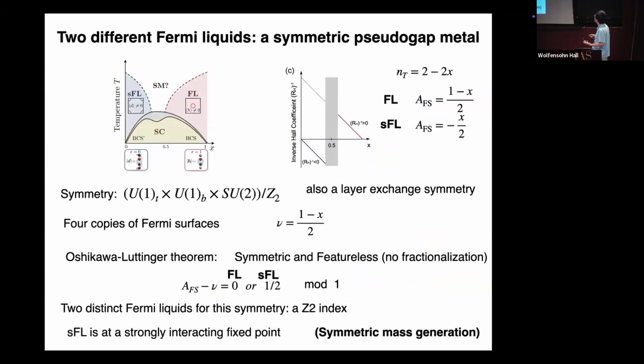It turned out it's possible if you consider the normal state. For example, in this regime, you can consider D condensed but H gapped. It turns out this gives you a small hole pocket. It's a Fermi liquid with a small hole pocket. The picture is almost trivial. X equal to 0 is just a round singlet. It's a vacuum. You dope some holes and form a small hole pocket. And there is another limit. You get a different Fermi liquid from X equal to 1. This is the regime which is empty. You dope electrons, you get an electron pocket.